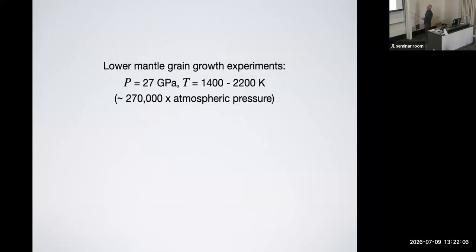So the grain growth experiments going back, the pressure that we did these experiments at is 27 gigapascals, which translates to 270,000 times atmospheric pressure, right? So that's the key challenge in these experiments, this is the development where you can go to lower mantle pressures with an apparatus that has a sufficient sample size so that you can actually do grain growth experiments without running into your capsule material. That's a relatively recent development, right? You have to keep these experiments not only at 27 gigapascals, but also at mantle temperatures, of course, because you want to know what the rates are at mantle temperatures. So that was the challenge, and this is what we did in the experimental sequence here.